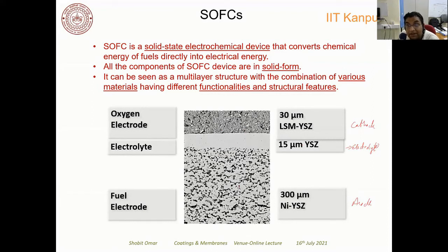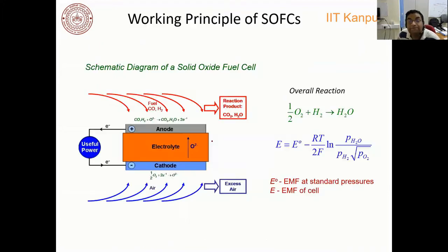So it's a multi-layer structure with a combination of various materials having different functionalities and structural features. And the important thing is that this is all solid form. There is no liquid involved, right? So this is the schematic of SOFC. Air flows along the cathode side, and the fuel flows on the anode side. Oxygen, when it comes in contact with the interface of electrolyte and cathode, this reaction will occur. If the cathode does not have any porosity, then the oxygen may not reach the interface region, so we require pores inside the cathode. This is the same reason why the anode also has some pores, so that the fuel can come in contact with the electrolyte and anode interface.